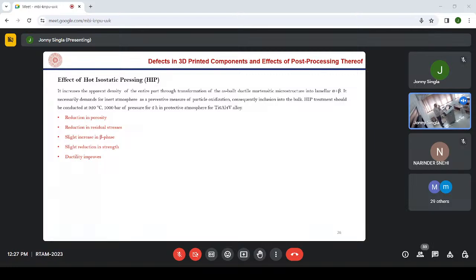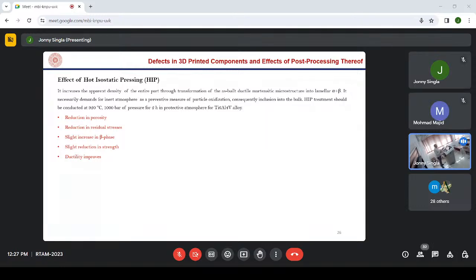If you give this HIP processing at 920 degrees Celsius at 1000 bar for 2 hours, it has significantly good results as far as defects are concerned. These are a reduction in porosity, which is a dangerous thing, and a reduction in residual stresses, which is quite desirable, a slight increase in beta phase, a slight reduction in strength, but ductility improves. All these things are desirable for titanium alloy. So HIP is the most desirable post-processing technique which can be adopted by a researcher for improving the performance of AM titanium 6Al4V alloy, and for that matter for other titanium alloys also.